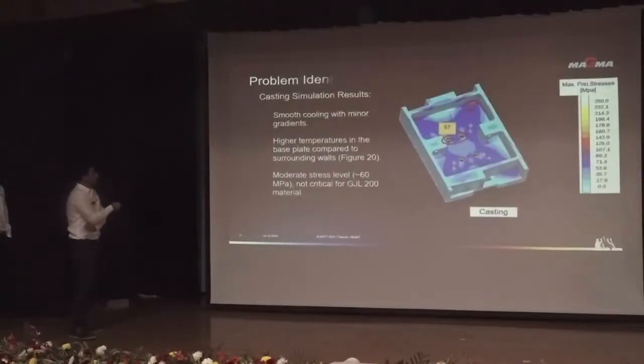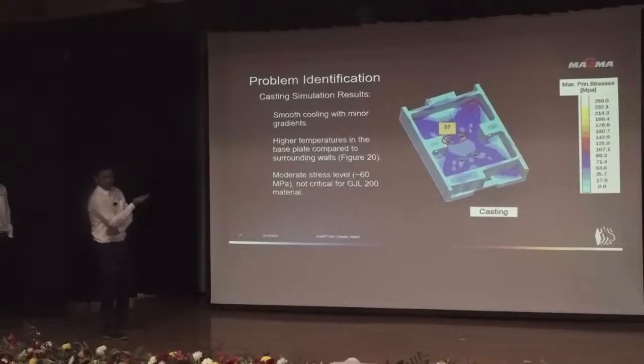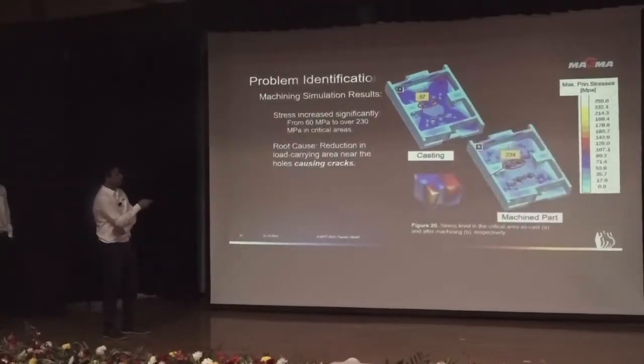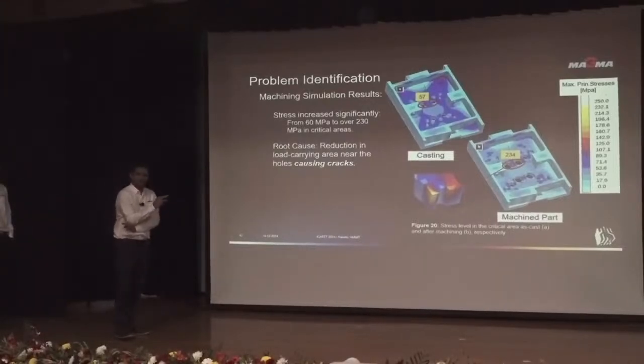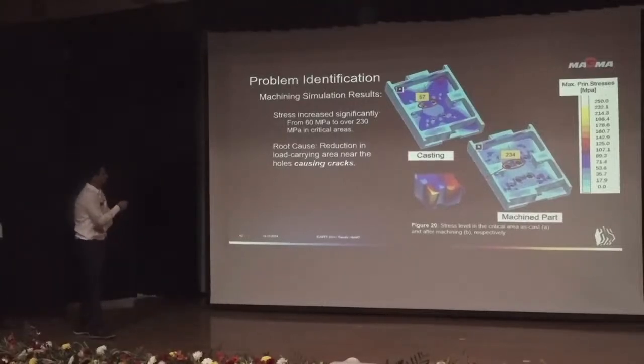So this is the as-cast part which we simulated. Here we find that only 57 MPa of stress is developed. But after machining, we found that the region had around 234 MPa of stress. So it was having a crack issue in these parts. So what did we do?